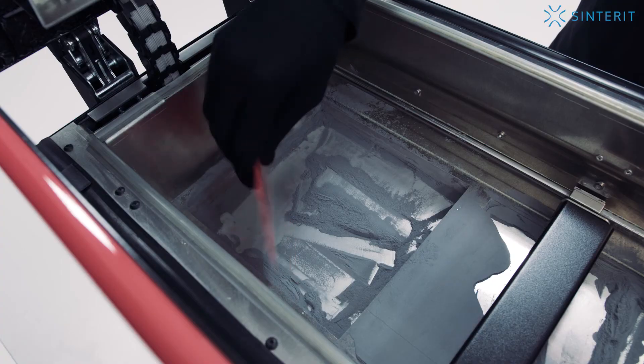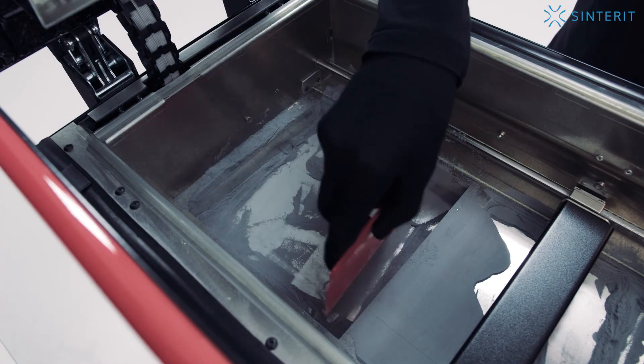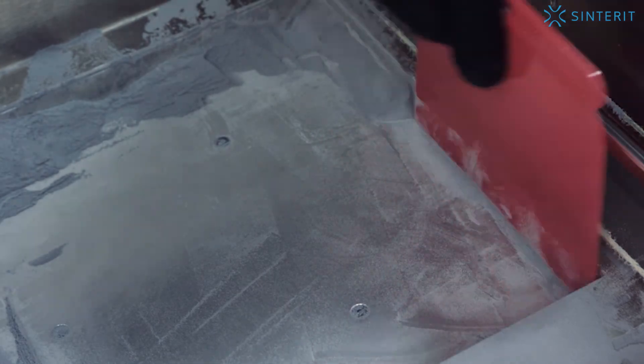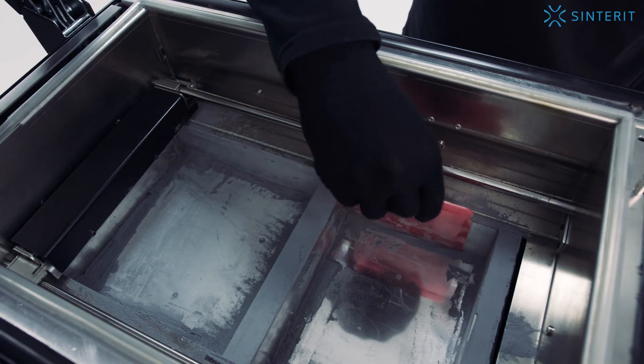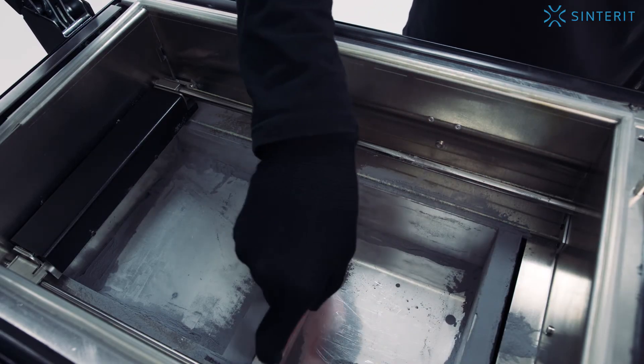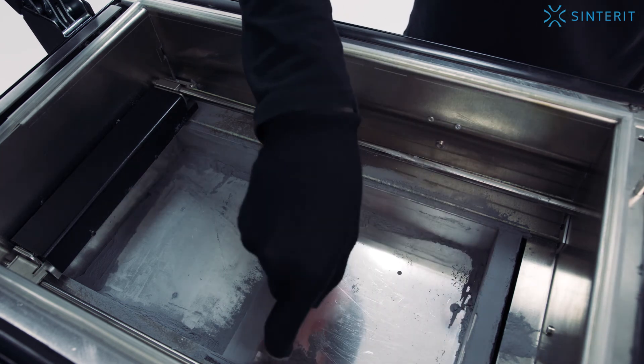Move the beds and delicately pat their surfaces in order for the PA12 to fall into the apertures. Thanks to this, we will seal the apertures, so that FlexaBlack, which has different thermal properties than PA12, won't glue the beds.